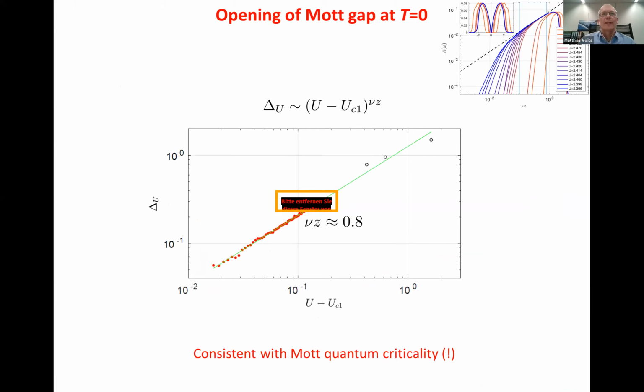If one goes away from the point where the gap closes, one can analyze how the gap opens. This shows the gap as a function of U minus UC1. Again on a log-log scale, this shows a beautiful power law with an exponent consistent with the notion of Mott criticality, all obtained within DMFT.